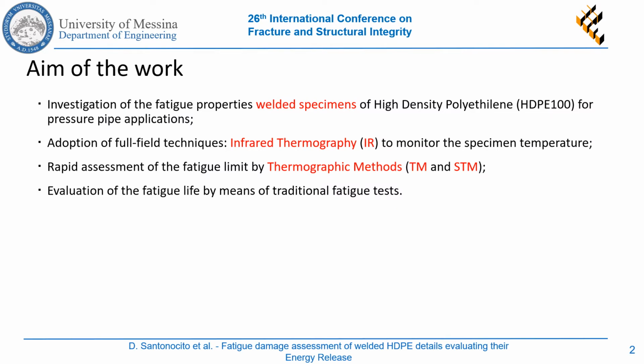The aim of this work regards the investigation of the fatigue properties of welded high-density polyethylene specimens adopting full-field techniques such as infrared thermography. The mechanical properties of the material were evaluated and the temperature trend of the specimen surface was monitored during static tensile and fatigue tests applying the thermographic method and the static thermographic method.